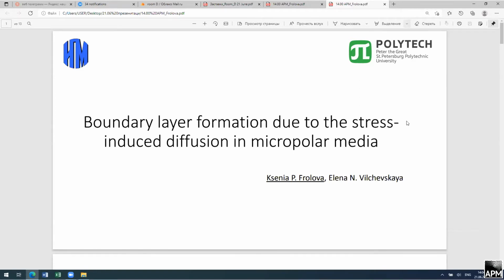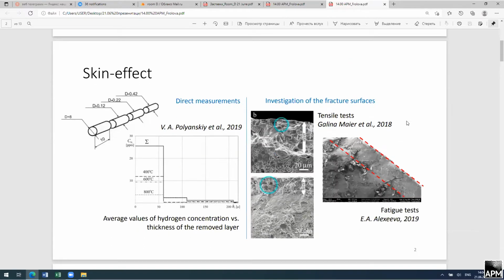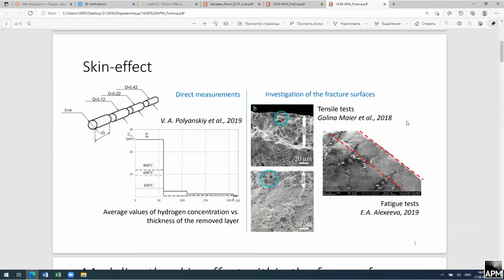Sometimes even small concentrations of hydrogen can lead to premature failure of structural elements and metal details. And a local increase in hydrogen concentration can also change material properties and its behavior significantly. Therefore, it is necessary to understand the real picture of the distribution of hydrogen through the thickness of the material. Usually it is believed that hydrogen is distributed uniformly through the thickness of the material.